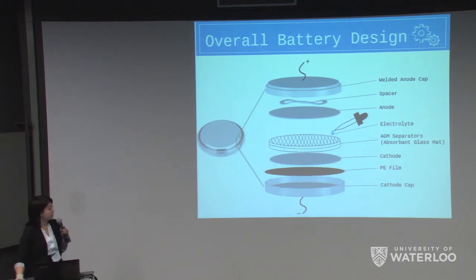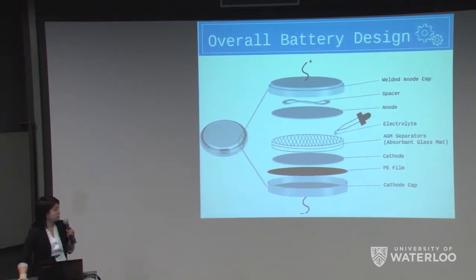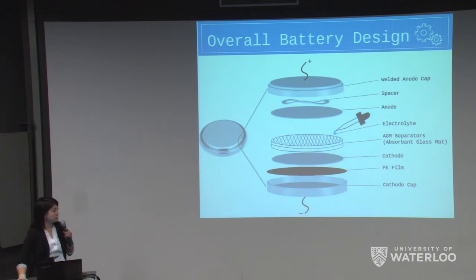After the placement of the cathode, this is where we place our absorbent glass mat separators, and we had 2 of them in our battery design. And then this is where we placed our electrolyte to be fully absorbed into these separators. Following this, we placed our zinc anode and then our spacer to be able to put pressure on the entire system to make sure that everything was in contact. And then finally, we finished off with our welded anode cap.